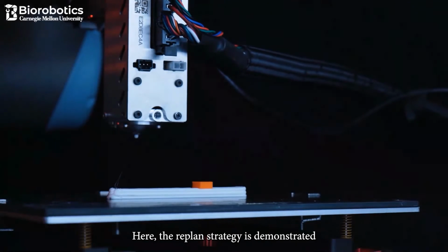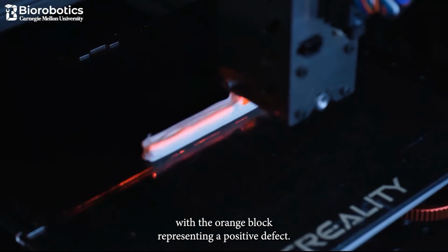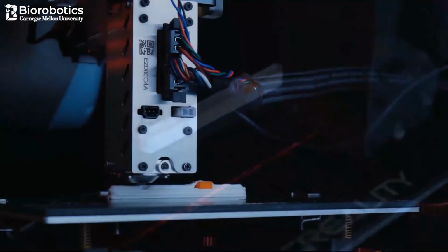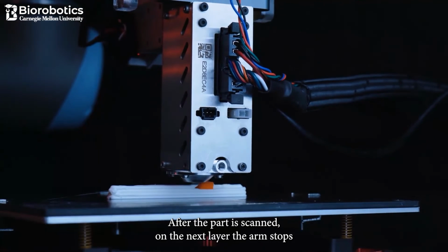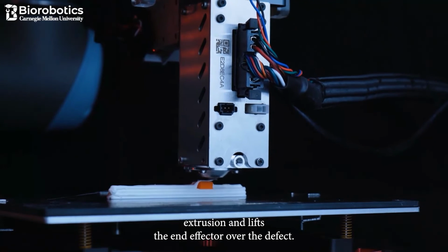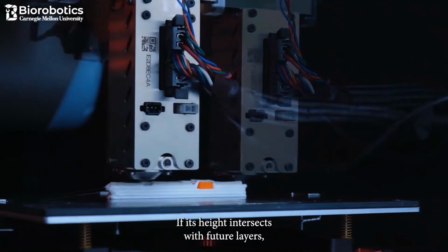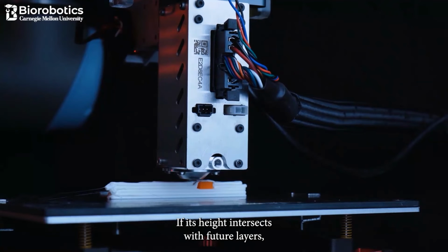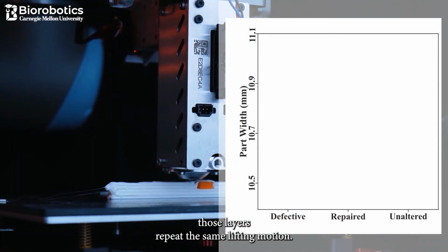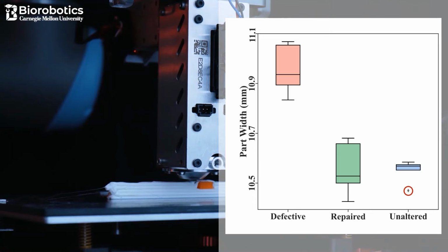Here, the replan strategy is demonstrated with the orange block representing a positive defect. After the part is scanned, on the next layer, the arm stops extrusion and lifts the end effector over the defect. If its height intersects with future layers, those layers repeat the same lifting motion. Our experiments show that the repair strategy brings the part geometry much closer to the unaltered, correct dimensions.